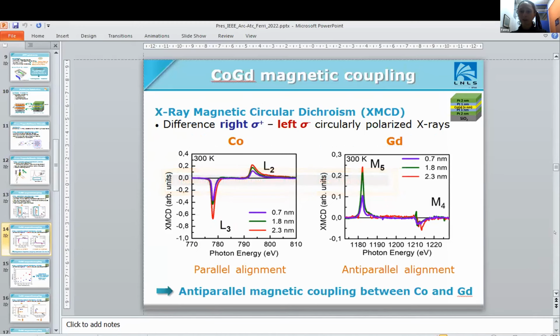So looking at the XMCD results, directly looking at the difference between the right, which is the plus, and the left, which is the minus circularly polarized X-ray. For the cobalt, looking only at the L3 edge, we see that for the whole thickness range, from 0.7 nanometer to the thicker, 2.3 nanometer, we have a negative signal. A negative XMCD means that the cobalt moment is parallel to the X-ray beam, and so parallel to the applied magnetic field.